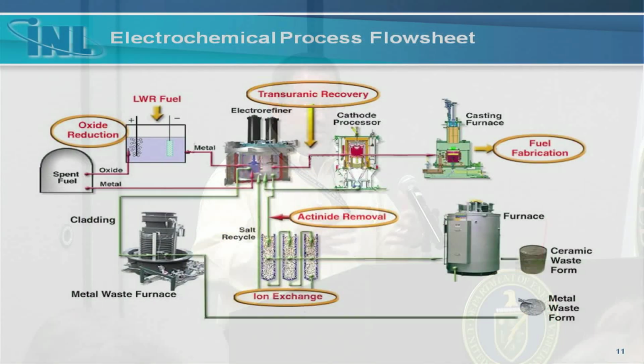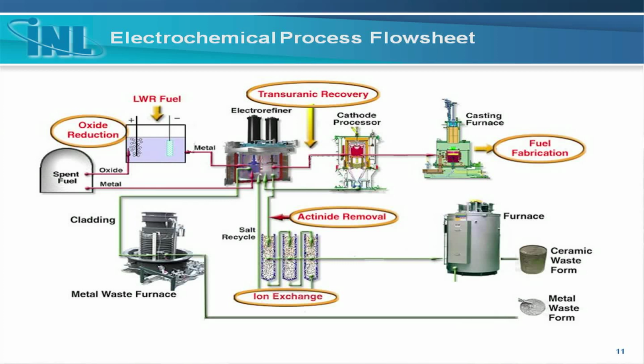But as we noted in Bob Jubin's talk, pyrochemical processing and aqueous processing are not mutually exclusive. Instead of doing this electrochemical process for reducing the oxides to metal, you could use an aqueous process to recover the transuranics from light water reactor fuel and feed that into a pyrochemical process instead. So there are ways to synergistically use the two processes to produce the best overall flow sheet. But again, let me stress, this flow sheet in the electrochemical processing is really focused on recycling fast reactor fuel or taking feed from a light water reactor fuel and getting it into a fast reactor. It's not for producing thermal reactor fuel for recycle.